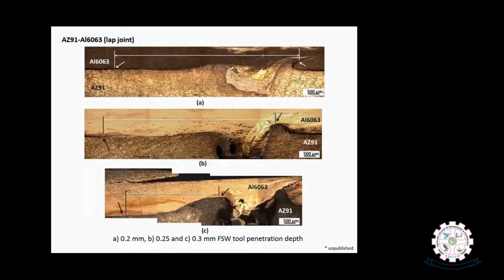And interestingly, you can see the joint formation between the aluminum and magnesium base materials, and the defect-free joint length was measured in the width of the weld joint, and we observed it with the increased penetration depth. Since it is a lap joint, tool penetration plays a very important role, and we altered the penetration depths in steps of 0.05 mm. With the increased penetration depths, we observed defect zones were increased. So therefore, the optimum penetration depth was found to be 0.2 mm. That is the excess penetration that we give to the tool to penetrate into the joint in addition to the